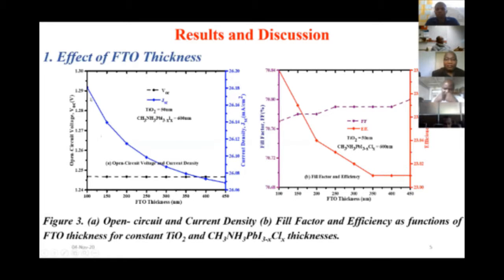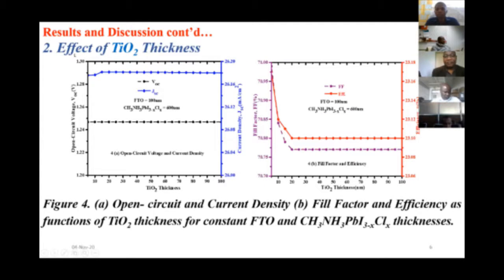There was also a decrease in current density, and the open circuit voltage remained constant. And again, when we changed the TiO2 thickness while holding other layer parameters constant, this is what we got. The open circuit voltage remained constant as we varied from 5 nanometers to about 100 nanometers. There was also a very small change in the current density. The same was observed for the fill factor and the efficiency.